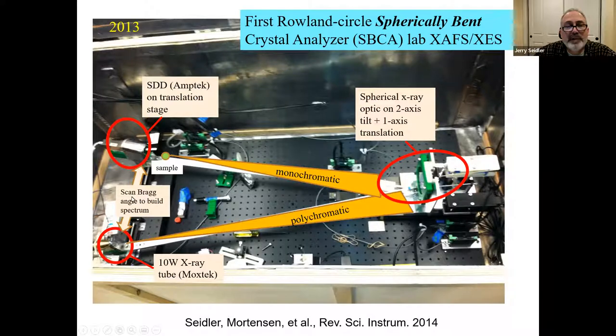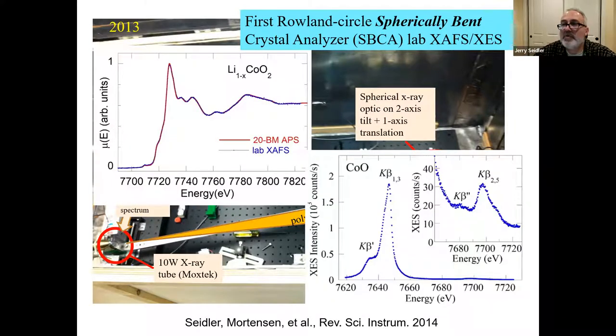And you would scan the source and detector symmetrically inward or outward and have a translation stage under the analyzer to make sure that you stayed in the Rowland geometry. And it worked, it just immediately worked. It was really painless. We immediately got data that had essentially perfect agreement with XAFS taken at 20-BM at APS. And we immediately saw that these laboratory instruments were surprisingly powerful for X-ray emission spectroscopy.